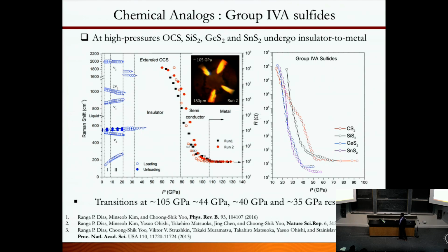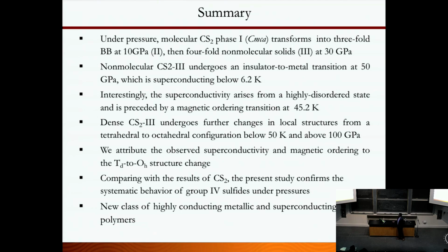So we kind of found a new class of polymers which has properties of superconducting and metallic under extreme conditions. This is something that we need to further study. If I summarize this one, under pressure, it goes to an insulator-metal transition, and then it goes to a superconducting transition as well. And it goes, as I mentioned, from 2-fold to 4-fold to 6-fold coordination.